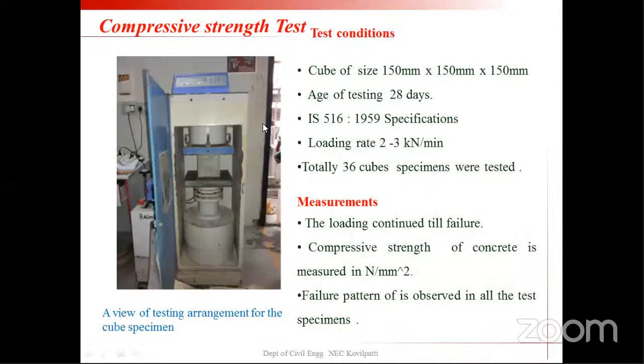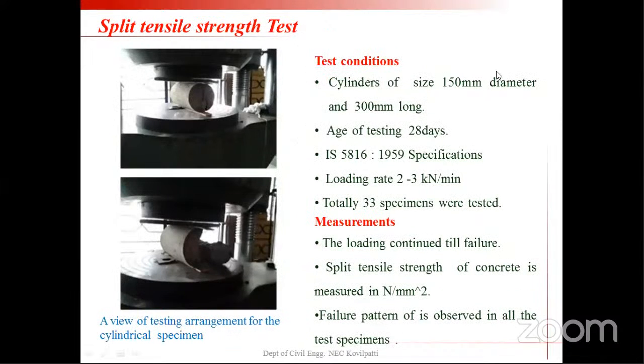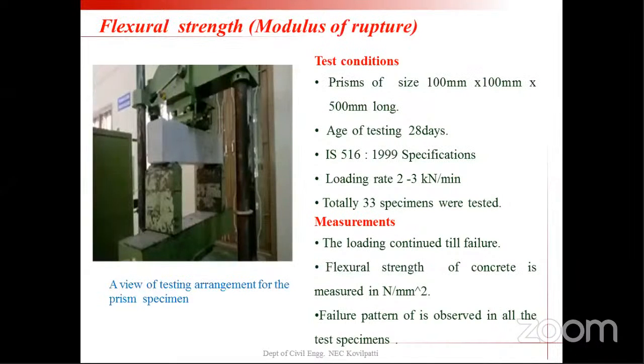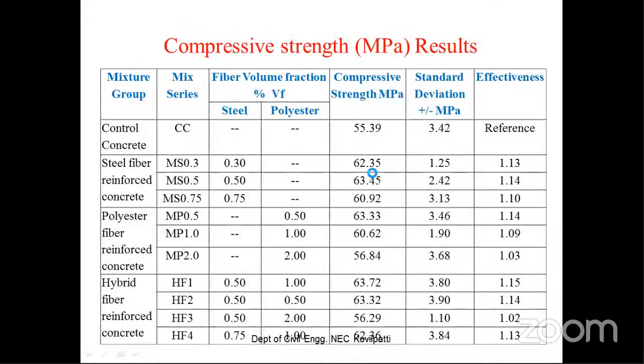And the test series has been as per the standard procedures mentioned in the IS codal provisions. For each series, 3 specimens have been tested. The compressive strength test has been conducted as per IS 516, and split tensile strength has been conducted on the cylinder at the age of 28 days as per IS 5816 specifications. Every time the failure pattern is observed, especially in case of FRC. And the modulus of rupture has been tested on 100 mm by 100 mm, 500 mm long specimens as per IS 516 procedure.